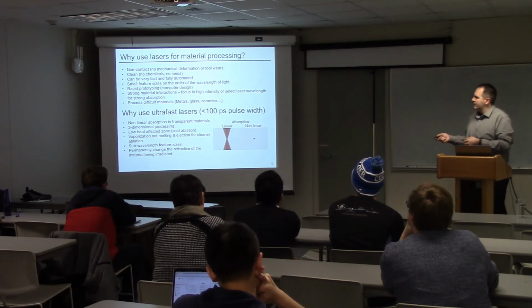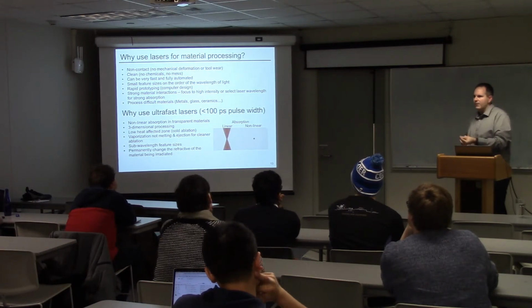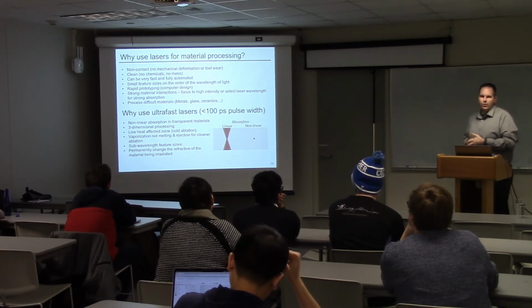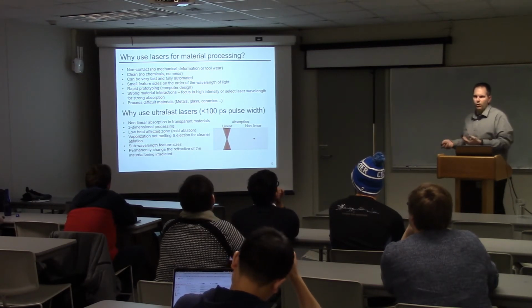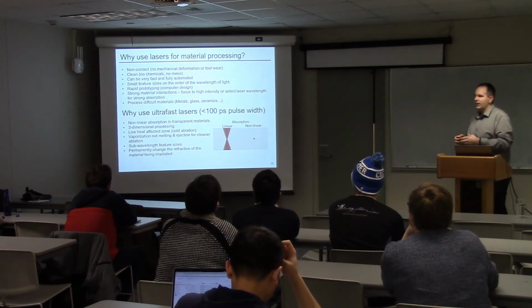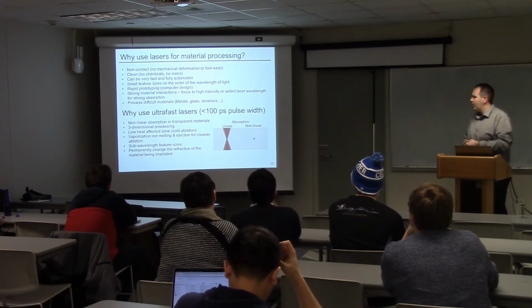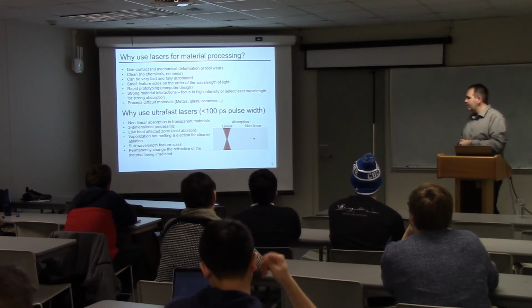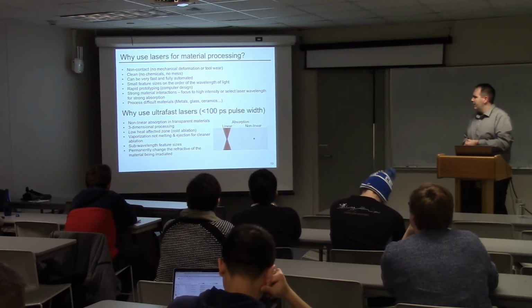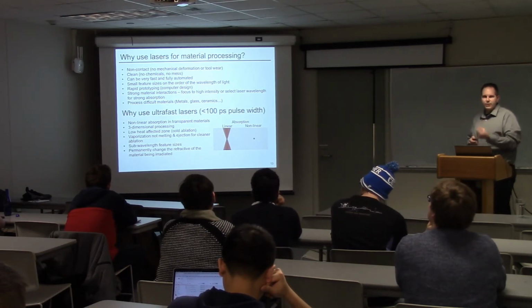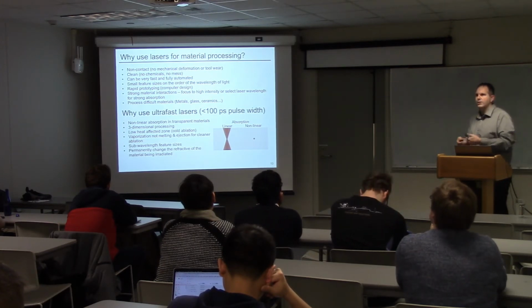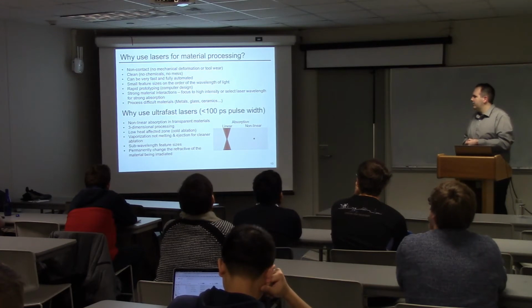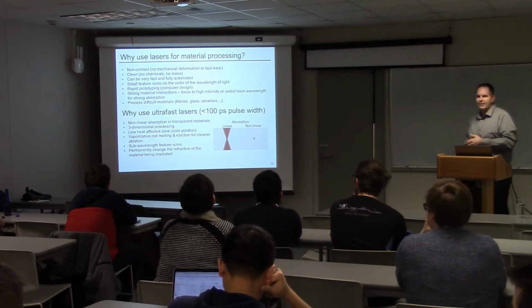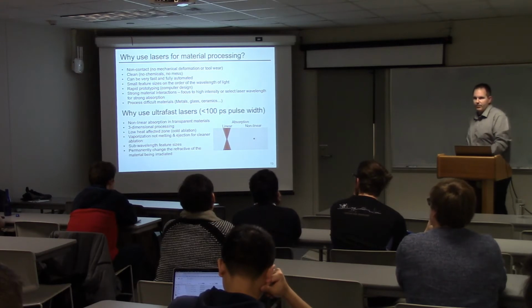And with these short pulses, basically you're hitting your target for such a short amount of time. There's a very small heat affected zone, and so there's this concept of cold ablation. It's not truly cold, but it's cold in the fact that there's not a large heat affected zone that you get at longer pulse durations. And that also allows us to do cleaner ablation as well. And here, you can actually beat the diffraction limit, so you can get feature sizes that are smaller than the wavelength because of these nonlinear interactions. And you can also, and I'll show some examples of this, permanently change the refractive index of the material in this manner with ultrafast lasers.